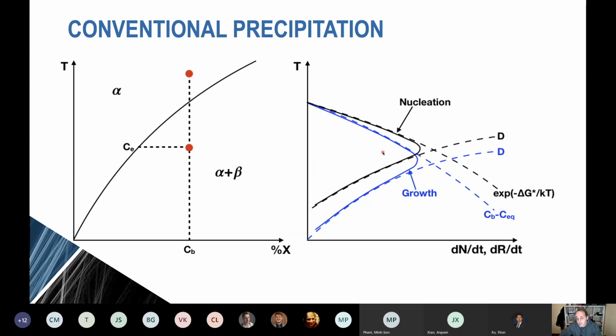That's quite important because from a mechanical properties point of view, usually what we're trying to do is make a very nice fine distribution of particles, fine and uniform. That means we want lots of nucleation and a little bit of growth. Now, the problem with nucleation is we want to have a large driving force, which means we want to go to lower temperatures. Here this is written in the context of a fluctuation type model for the nucleation process. But even if you don't believe in that, in aluminium alloys, whatever the mechanism of nucleation is, certainly we need a thermodynamic driving force.